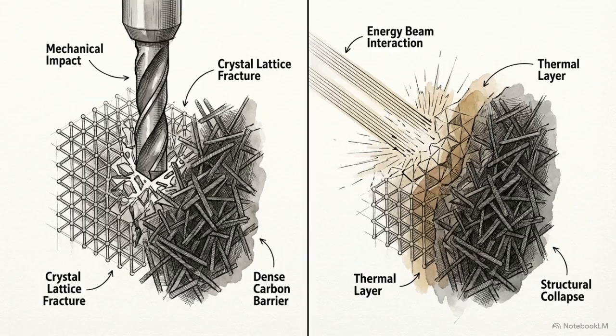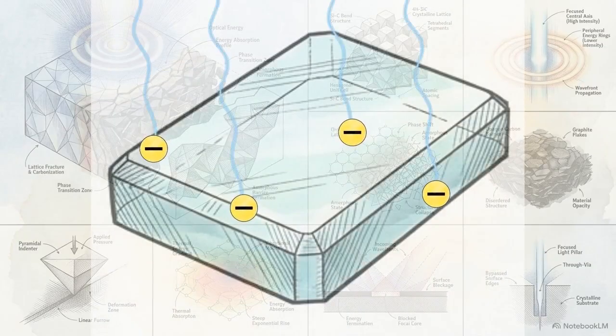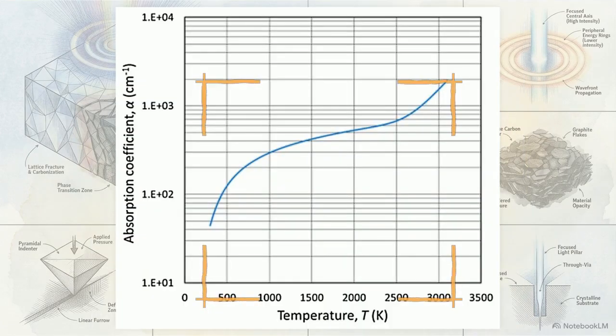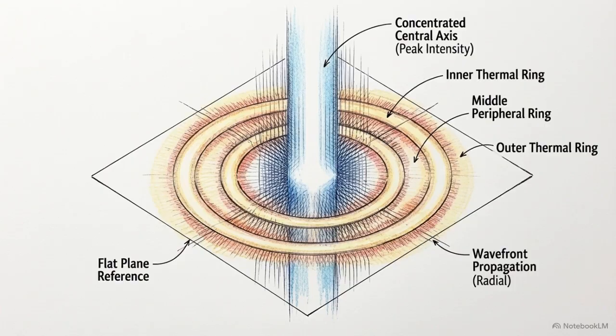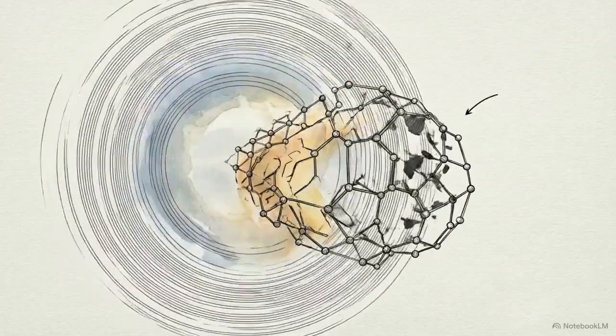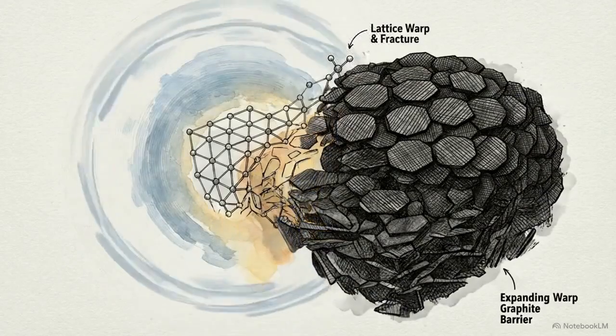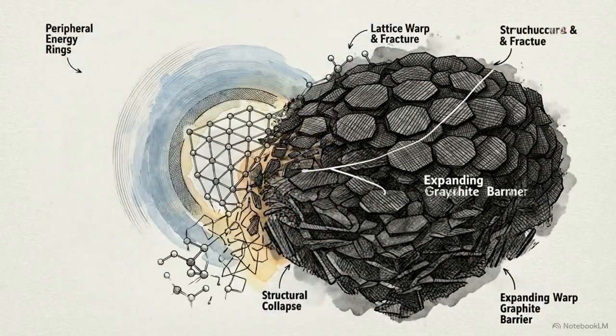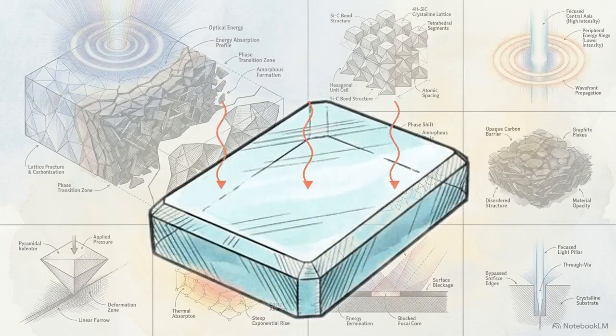This mechanical phase change explains the limitations of nanosecond laser ablation. The dominant energy transfer mechanism in this context is free carrier absorption. This graph shows how the absorption coefficient increases with temperature. As temperature increases, dopant ionization and valence band activation cause the absorption to scale sharply. When we re-examine the Bessel beam's spatial profile, the impact of the peripheral side lobes becomes clear. These lobes deposit enough thermal energy to trigger the same crystalline to amorphous to graphite transition observed in the mechanical data. The resulting graphitic surface layer has a narrow bandgap and is opaque to the near-infrared laser light.